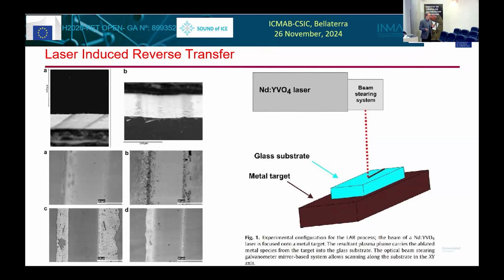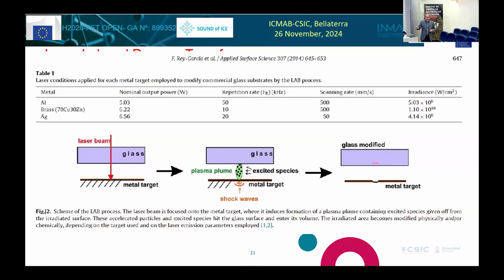But before that, we started doing this technique years before in Santiago with our colleagues there, for optical applications, just to see if we could generate optical waveguides in glass. And so what we did, this is the simple experiment. We have a glass, transparent to the laser. We go through the glass and generate an ablation plume in the metal below, which is in contact with it. And so we can generate any drawing, and this will cause the glass to be deposited with metal particles. And that's what you see here. This is the original work. This is the process with a scheme.